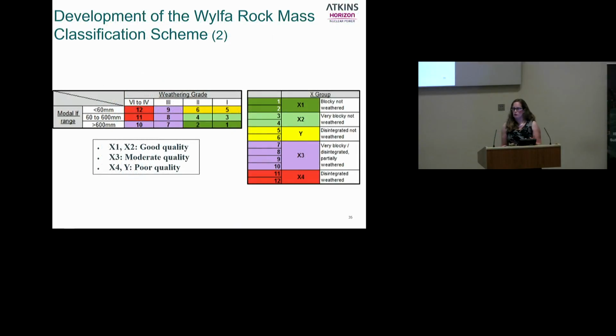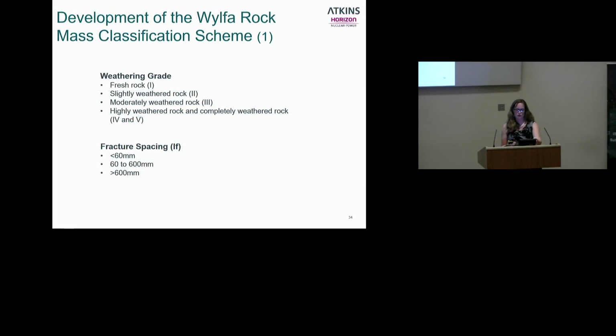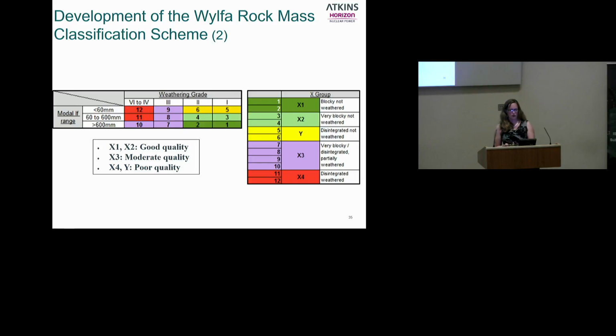We did some trials, and it was looking like using just these 2 parameters, it gave us a good handle on where the poor quality and where the good quality rock on site was. By using 2 parameters split into those 4 weathering grades and 3 fracture spacings, we came up with a 3x4 matrix, so 12 sort of subgroups, which would be too many to sort of get your head around in an interpretive report. So we grouped them together and ended up with 5 main groups. They got called X groups just because X is a generic term. So we have the 5 X groups.